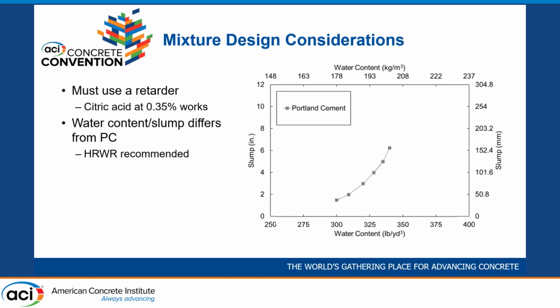So what I have here is slump on the y-axis and water content on the x-axis, and this gray line is what ACI 211 says is the rough relationship between slump and water content for the size of aggregate that we use at the University of Arkansas. So we made some BCSA mixtures at different water contents and different citric acid dosages and compared to this guidance.